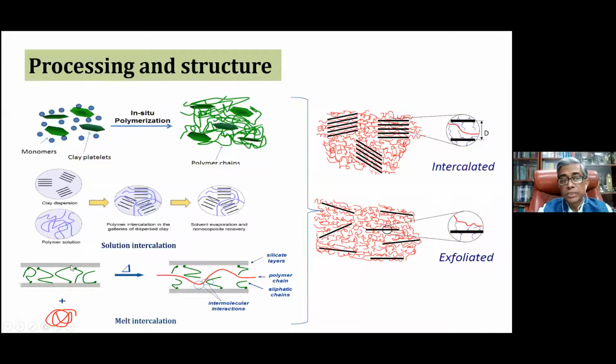It is more challenging. I was trying to tell you that you have different layers. You have these interlayer ionomers, oligomers, the tallow material and all that. We shear, but we also want the polymer chain to enter and go through this interlayer distance. The red one is the polymer chain which is going in, and there are lots of modifications you have to do for that.